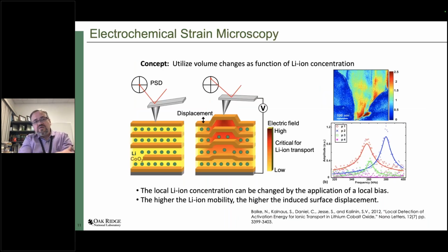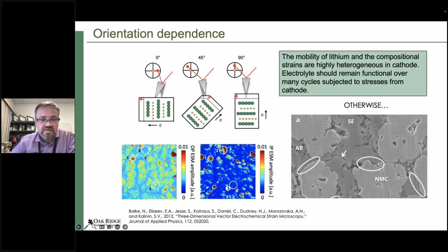How inhomogeneous? Well, we have this special tool developed here at Oak Ridge called electrochemical strain microscopy. It is basically an atomic force microscope, AFM, with a conductive tip, and you can apply a bias to your tip and the substrate, which creates an electric field, which in turn moves the lithium ions inside the crystallographic lattice, which in turn creates the strain. And that strain is measured by the same AFM tip. So in that way, you can get the strain fields on top of your fully dense cathode with nanometer resolution, really. And if you scan some area, in this example, this is lithium cobalt oxide, you will see highly inhomogeneous strains here.